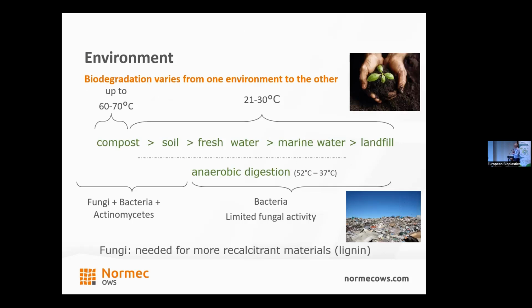Now, also important to know, the environment is an important factor for biodegradation. A material that is compostable may not be biodegradable in water, in marine conditions, or in soil. And there are two main reasons for that. Compost is generally considered the most aggressive environment, certainly industrial composting, because there you have high temperatures, up to 60, 70 degrees, and the presence of a lot of fungi, bacteria, and actinomycetes. These fungi are often needed to degrade the more recalcitrant materials.